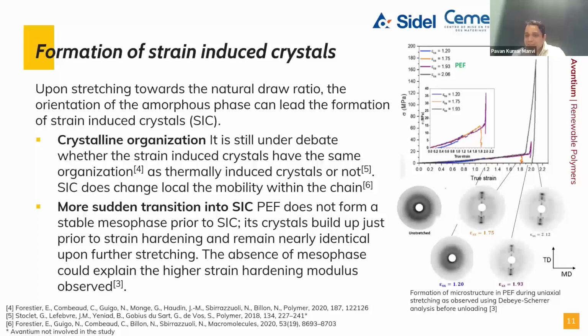That means there is no stepwise transition from the halo phase to the oriented phase and oriented crystalline phase, and it is just a sudden transition at some point of orientation and stretching, and then it remains the same. It becomes more oriented. More oriented means intensity is again more and more diverted towards the equators. But this change, for example, here we can see from the draw ratio of 1.2 to 1.75, is quite significant, that there is no mesophase and it is directly converting into the crystalline phase.